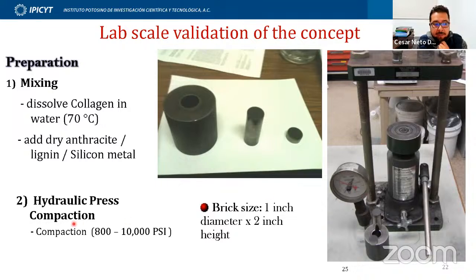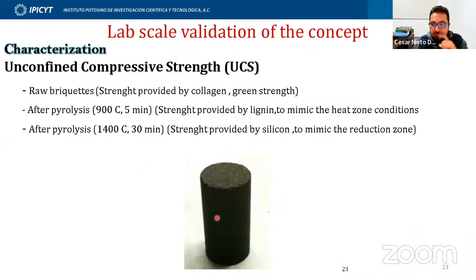We make this brick by putting the mixture inside this die, and then we apply some compaction pressure. And we got this small briquette, 1 inch in diameter and 2 inches high. Here is a picture of the small briquette. The main characterization that we did to validate this concept is that we take this briquette and apply pressure, which is the unconfined compressive strength, using the universal strength machine. We apply pressure with 2 plates, and we record the maximum strength of the briquette.